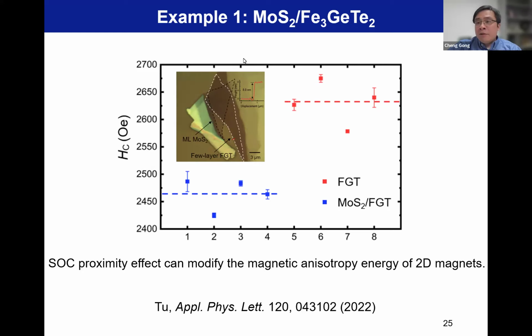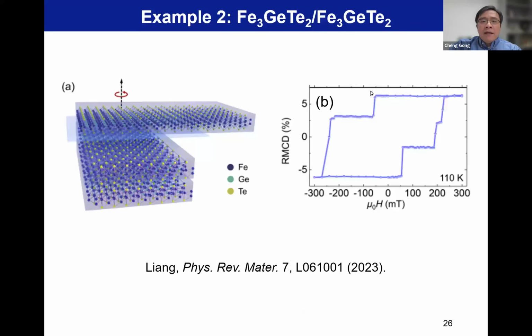The reason is simple, moly is a heavy element. The strong spin-orbit coupling arising from moly actually will change the magnetocrystalline anisotropy of the neighboring FGT. The other example is also very simple. My student just put two FGT, iron germanium telluride, flakes together: exfoliate one, exfoliate another one, put them together, and they find two coercivities, sometimes probably even more if you look into detail. But anyhow, you have two jumps, so two coercivities, one coercivity smaller, one larger.